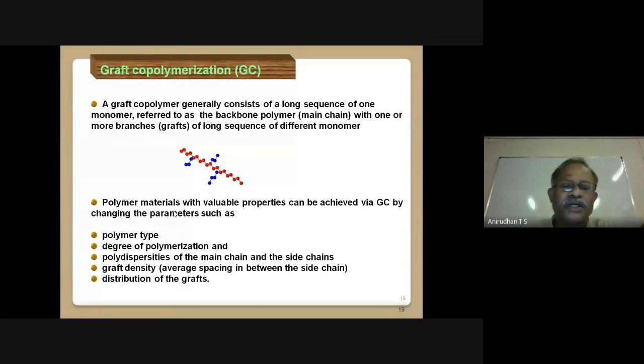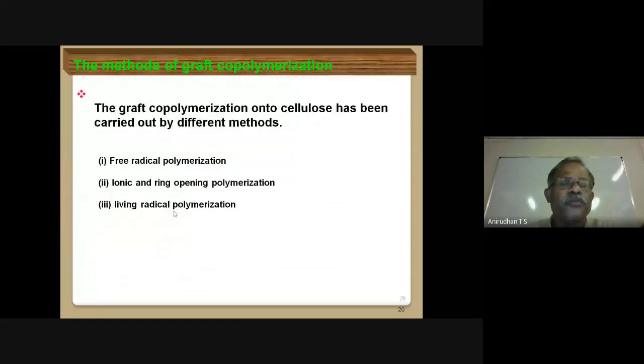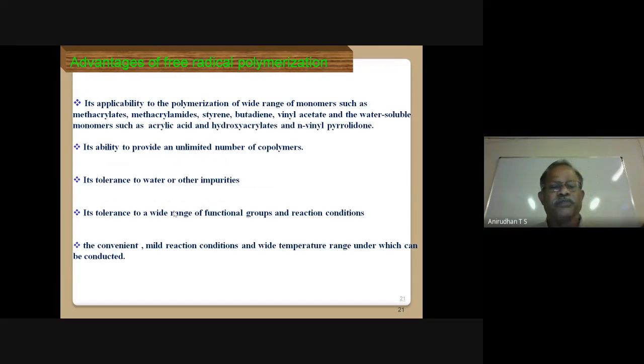And of course, polymer material with valuable properties can be achieved via graft copolymers. These are the advantages of this because we can modify the monomer type. Degree of polymerization may vary. Polydispersity of the main chain can be changed. Then graft density can be another factor to control these properties, and distribution of grafts also determines its properties. So we utilize these different factors during the preparation of graft copolymers. And of course, graft copolymerization onto cellulose is carried out by different methods: free radical polymerization, ionic or ring opening polymerization, living radical polymerization. Among these three different polymerization methods, we prefer free radical polymerization because it has its own advantages, A to Z advantages.